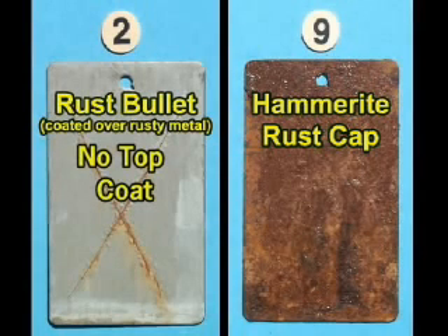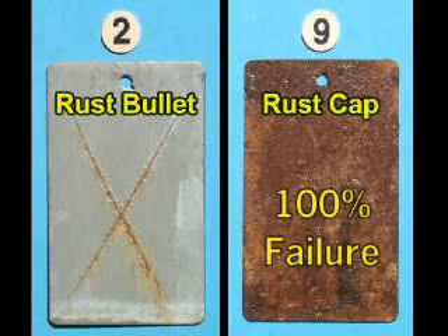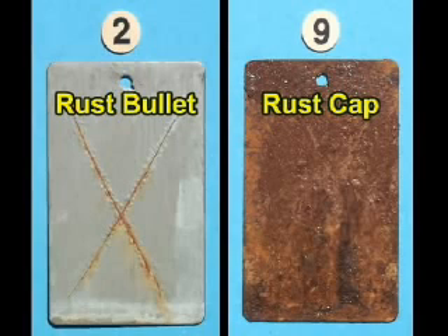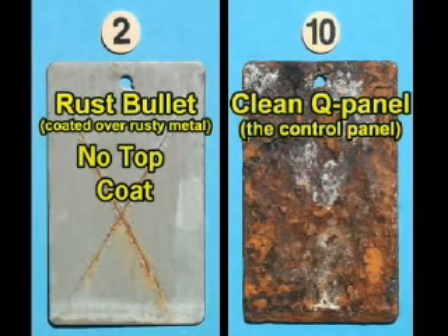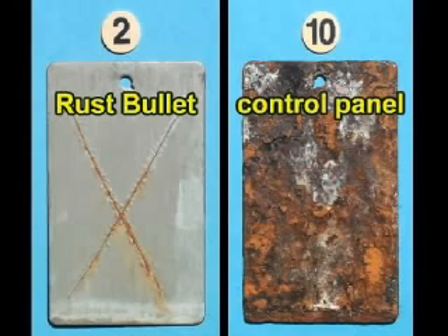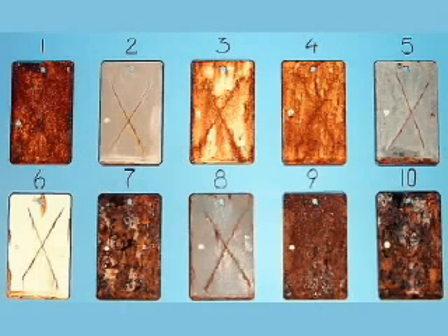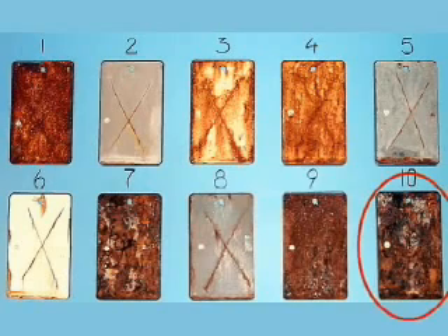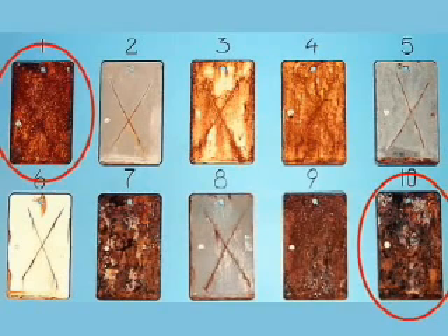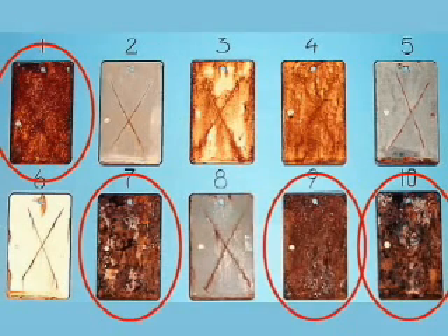This test panel has been coated with Hammerite Rust Cap. Here, there has been a near 100% coating failure. There seems to be very little difference between this panel or the control panel that hasn't been coated with anything. This is the uncoated control panel. This test panel was used to demonstrate how rust reacts on untreated metal in the same environment as the coated test panels. What is interesting is how similar this untreated control panel is to panels 1, 7, and 9.